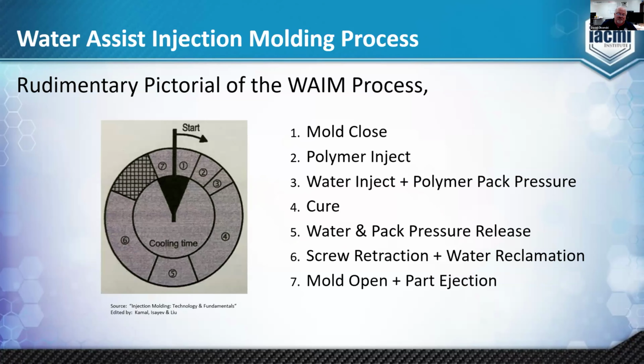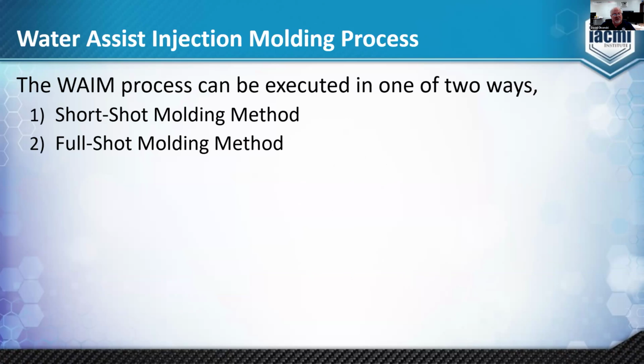So, a rudimentary pictorial of the water assist process, right? You'll have the mold close, you'll inject the polymer, and at some point in the injection, you'll inject the water. You'll then apply a pack pressure through water or the polymer. You'll let the material cure in the tool. You'll release the water and pack pressure. As the screw rotates, you'll reclaim the water from the cavity, the mold opens, and the part ejects.